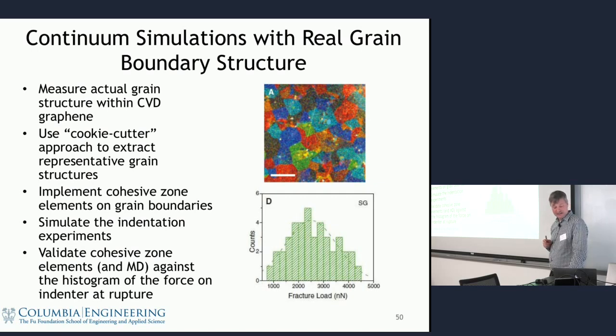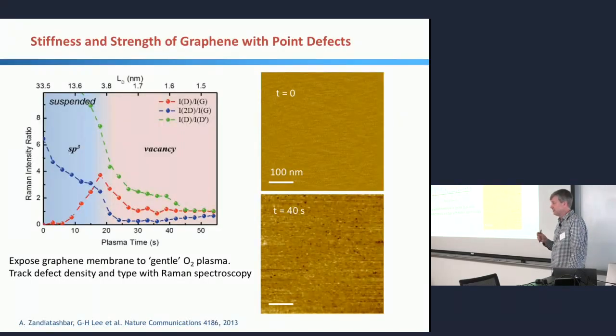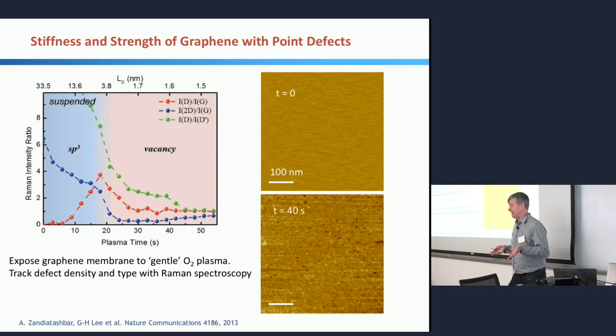So the second experimental study is something we've looked at to put point defects into graphene. Again, this is motivated by the same thing. In a real mechanical application of graphene, you're going to have large sheets that are going to have grain boundaries in the sheet, but you're probably going to have to cross-link the sheets as well. And when you cross-link the sheets, you're going to have to put in point defects for those cross-linking sites, right? So what do those point defects do to the strength?